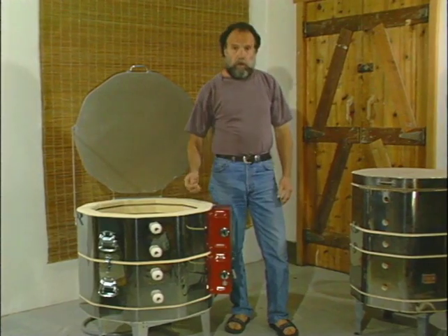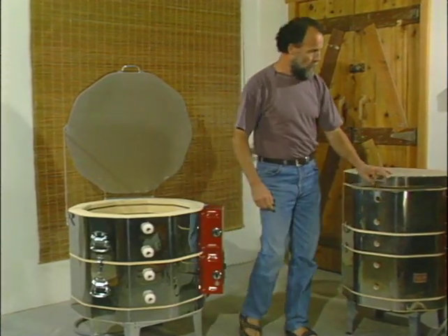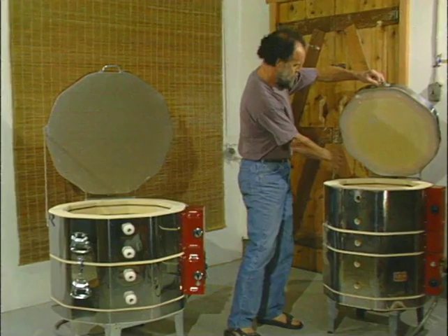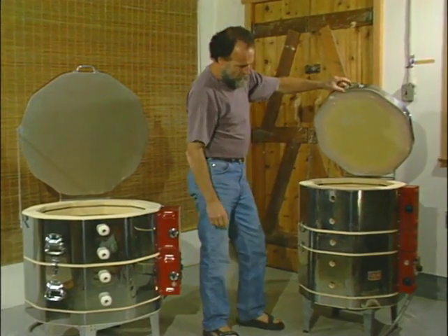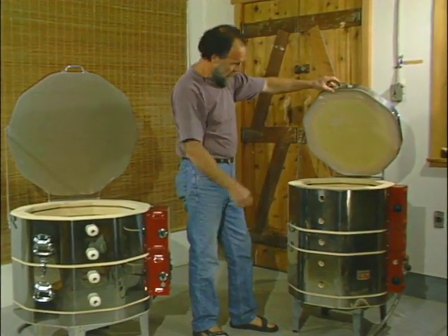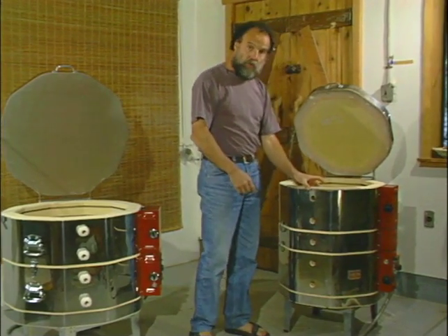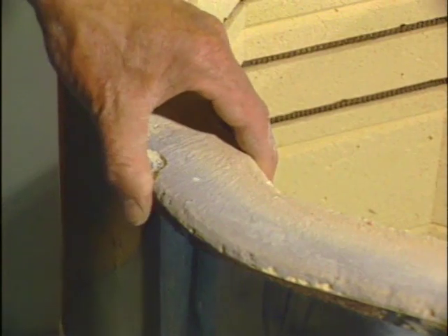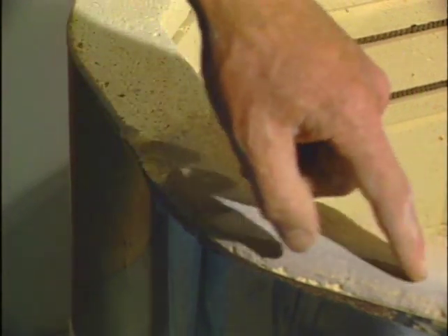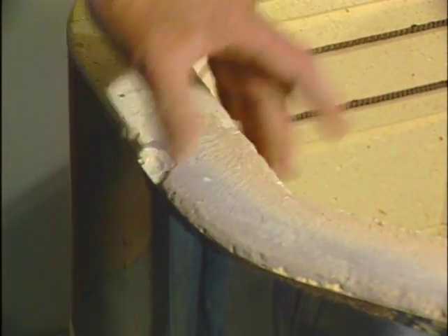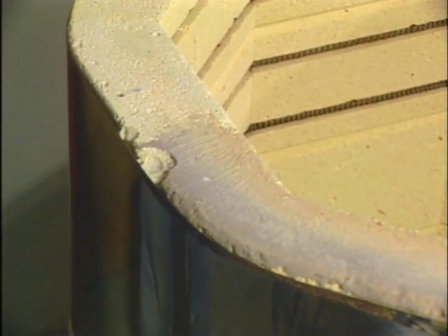By contrast, we could look at an older Skutt kiln that we recently purchased and have a look at a few salient details here. First thing to notice is that the walls on this are only 2 inches thick by comparison to the previous kiln, which were 3 inches. This kiln's rated at cone 6.